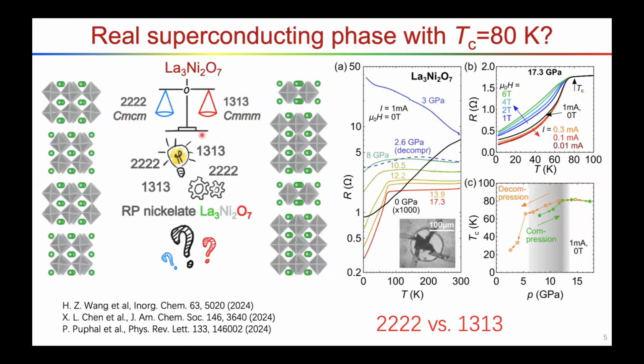Okay, so after the discovery of the superconductivity on this 327 compound, this bilayer compound, at that time many groups were working on RP nickelates, and at some point people questioned what's the origin of the 80 Kelvin superconductivity, because there are always some stacking faults on these RP nickelates. For example, this 1313 phase has the same chemical formula. And in this work, they even see a drop at 80 Kelvin on this 1313 phase. So, which is the real superconducting phase corresponding to this 80 Kelvin superconductivity?